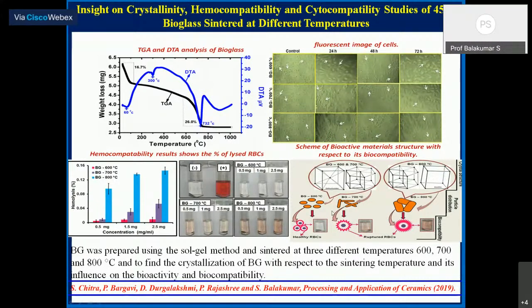The change in the shape also changes the functionality. See the lysis of the blood from the donor's blood: you can see that the hexagonal plates have very high hemolysis, while the others are less. But of course, the control 0.3 is an acceptable region. All are well below, but there is a significant difference between these two regions. These pictures show the blood and a negative control that we have taken, and added together, you can see the lysis part. All the platelets are lysed.